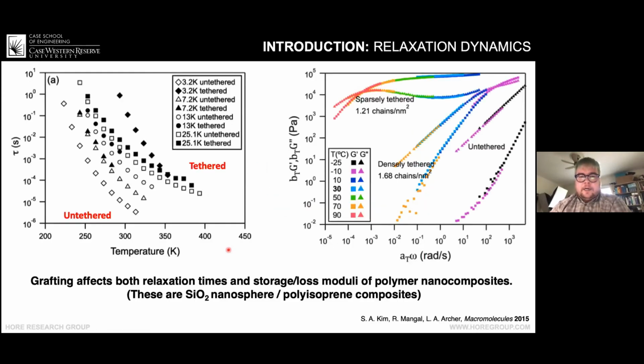The next thing that I want to talk about is the dynamics of the polymer chains when they're grafted to nanoparticles. That's going to affect the mechanical properties that you can maybe see in this graph on the right here, where the storage and loss modulus of these composites was measured as a function of the grafting density of the polymer chains. And you see you get different responses, whether the chains are untethered or not grafted to the particle, at a high density or at a relatively low density.